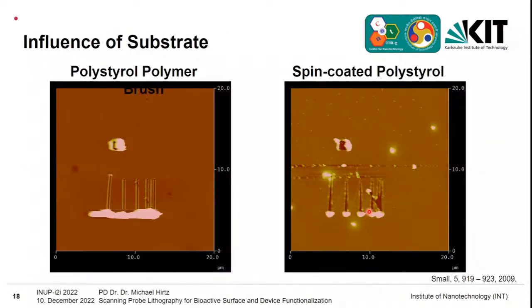So how does that look? I show you here two images where you can see the influence of substrates on this. You see already a difference between the two. Here there were lines scratched by the AFM and a square. Here basically the same is done, but you see that there are not really straight lines, they widen a bit. What you can also see is that the scratched out material, of course, needs to go somewhere. So you can see it here on the side.